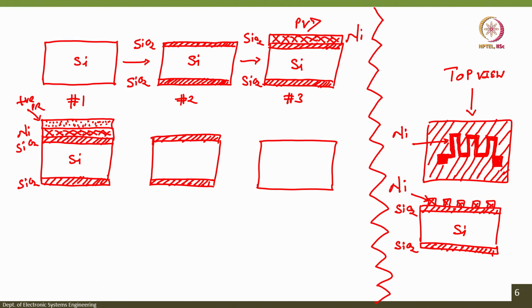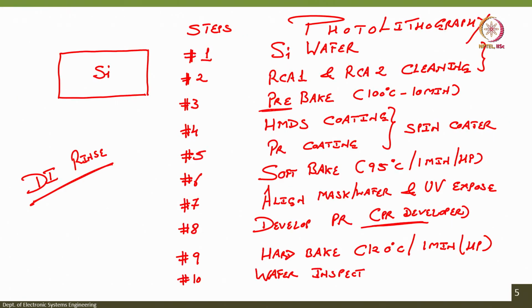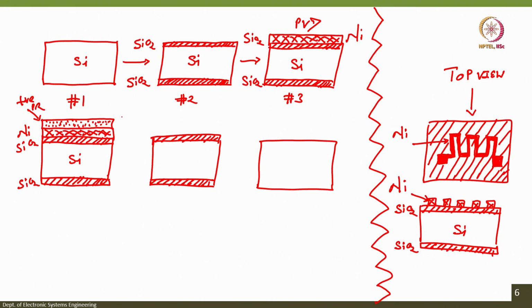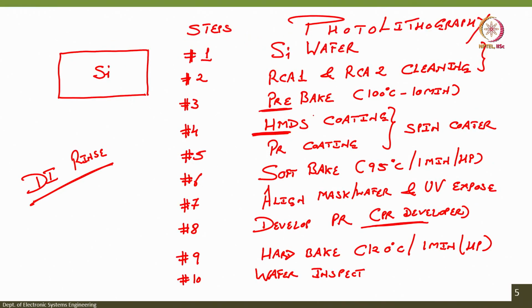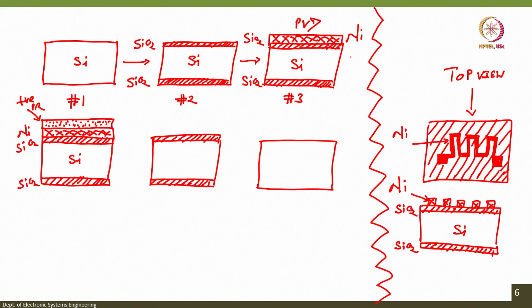Positive photoresist. After positive photoresist, what are the steps? Now, you see, pre-bake is done, HMDS coating is done, and then we went for PR coating. Okay. So, I am not going into all these details. It is assumed that after the nickel, if you want, you can use HMDS, or you can just directly spin coat the photoresist. HMDS will improve the adhesion, but it is not required that every time you have to go for HMDS. So, you can directly go to PR coating. Here RCA1 and RCA2 cleaning should be done when we get the silicon wafer. After silicon wafer, we perform the cleaning step, then we do the pre-bake, then we grow this thermal oxide, then you deposit nickel using PVD, then you spin coat positive photoresist.